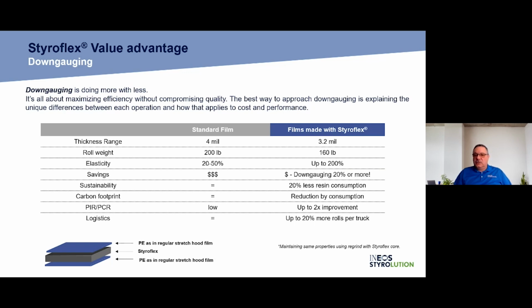On sustainability efforts, you're basically using 20% less resin consumption. With that being said, you're going to get a lower carbon footprint, which is a reduction by consumption. And also what we have found is when you utilize PIR or PCR content, many times you can get up to 2 times more loading with a Styroflex-based film than in a typical olefin-based film. Also, logistics equals 20% more rolls in the truck due to the smaller roll size. As you can see from the pic at the bottom, a Styroflex-based film would basically contain about 50 to 60% in the B layer, the core layer, compared to an olefin-based film, where you would have that olefin-based elastomer in the core. Next, please.